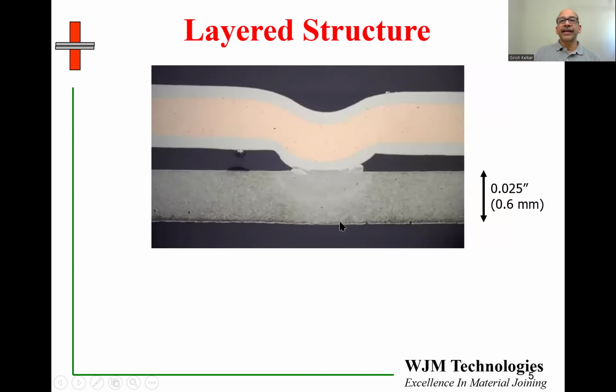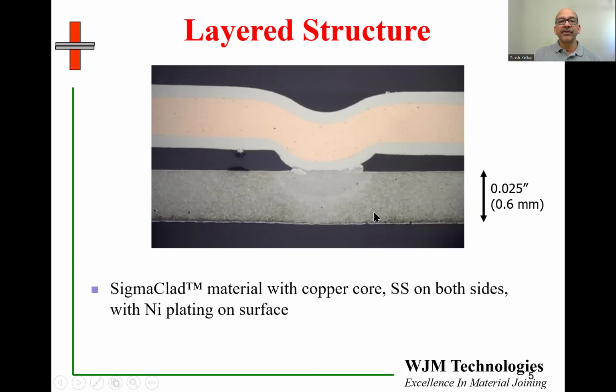In some situations where we want higher current capacity, even a nickel tab by itself may not be sufficient. So here we use a composite tab. In this case, I'm showing the tab on the top. There was a projection on the tab, which has been welded to the battery can. And the scale of the battery can, you can see over here, is about 0.6 millimeters. The tab is a composite, which has copper on the inside, stainless steel layers on the outside, and a nickel plating on the exterior, which you cannot see because the plating is too thin.